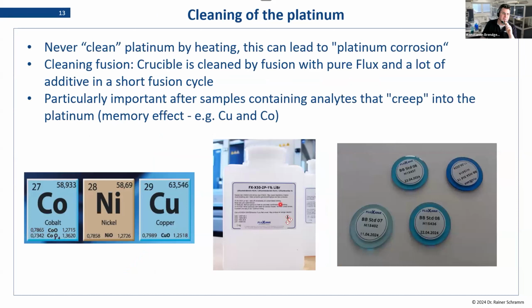There is an old habit that people use platinum ware and for cleaning they heat it up. They don't put anything in there, but they put it in the furnace so that every contamination or every dirt gets burned away. That is a very bad idea. The problem with cleaning platinum by just heating it up to a high temperature is that it can cause this so-called platinum corrosion. We'll get into the details there. So we definitely recommend not to do that.